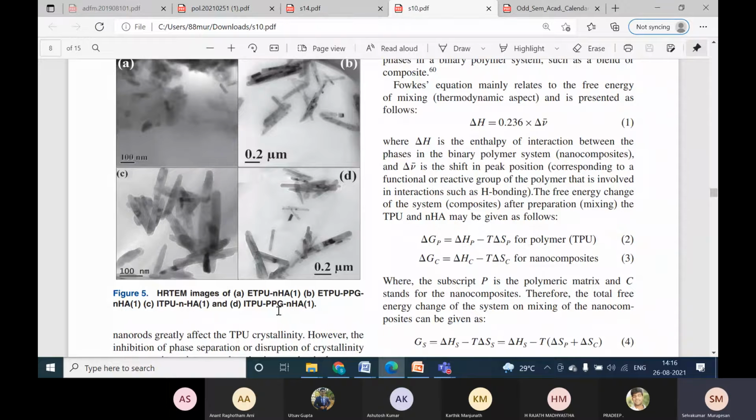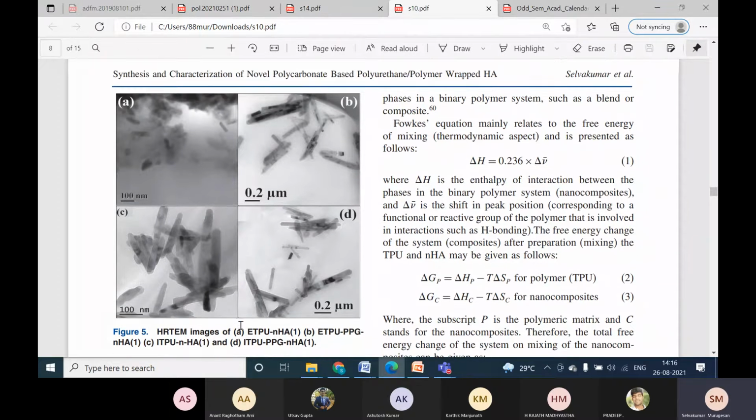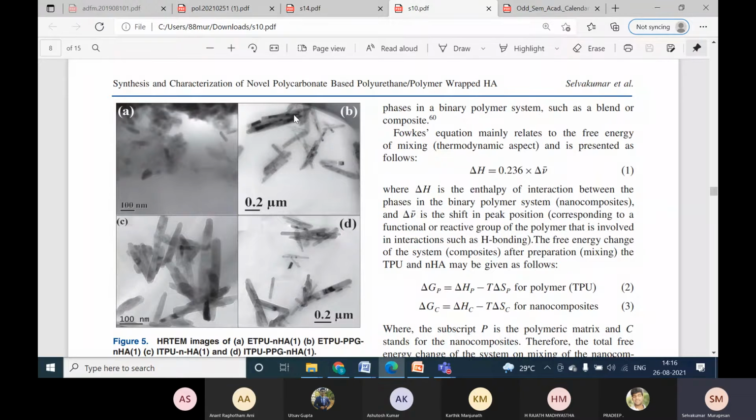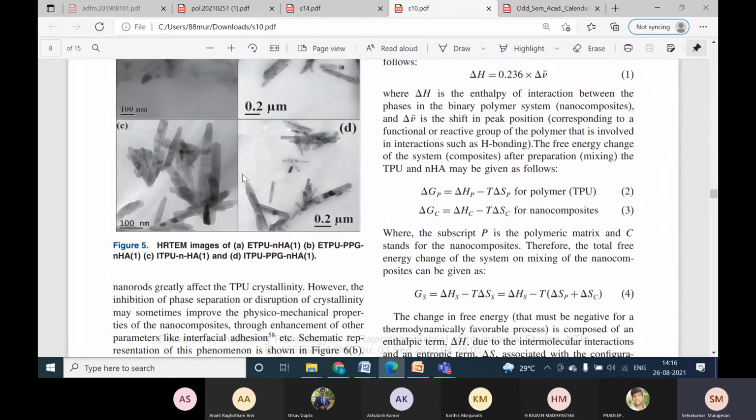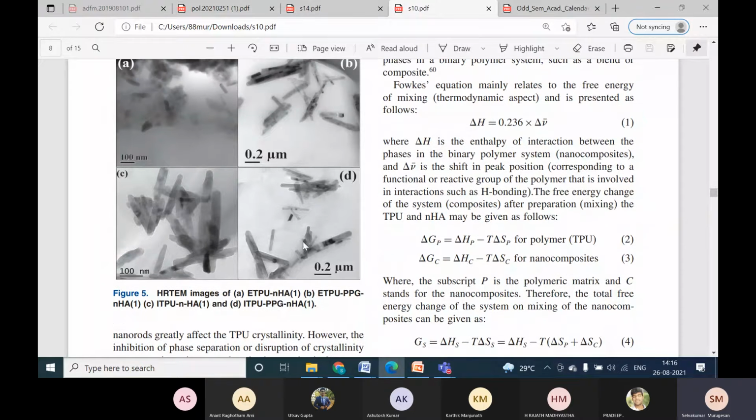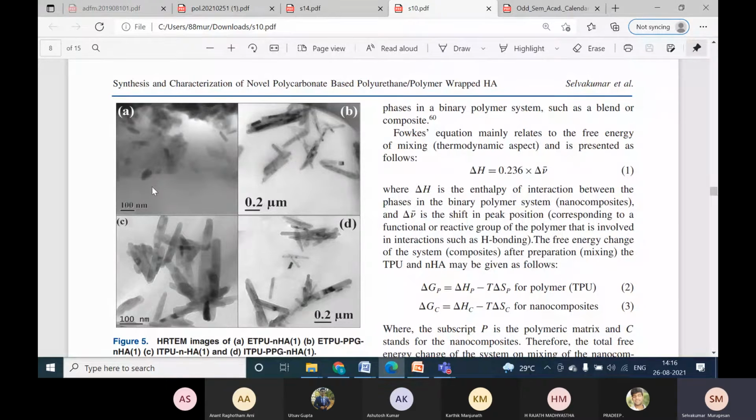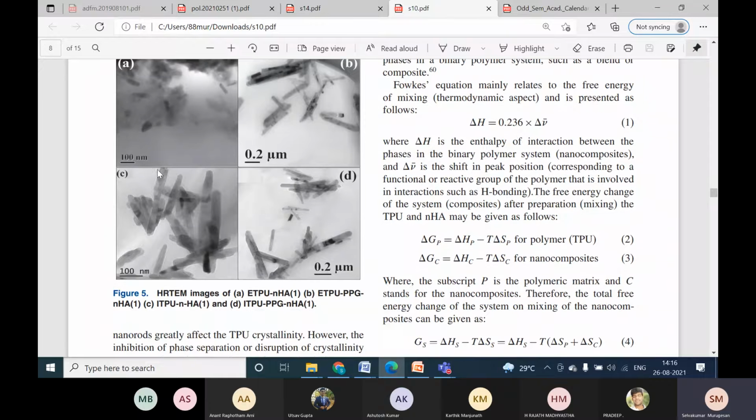Okay. And yeah, you can see here the ex situ prepared one has slightly aggregated structures. But in the in situ prepared composite, you can see the filler dispersion is pretty good actually. In fact, the nanoparticle size was also retained. But in the ex situ case, you can see some of the nanoparticles got broken, their surface got defects, some distortion happened. So in the in situ composite and the ex situ prepared one, the in situ one shows very good morphology.